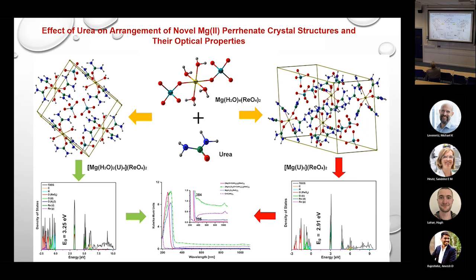Another result is that the conduction band consists of urea, oxygen, and nitrogen states, and the energy of the conduction band increases. So this led to this difference of the band gap, which is reflected in the optical properties.